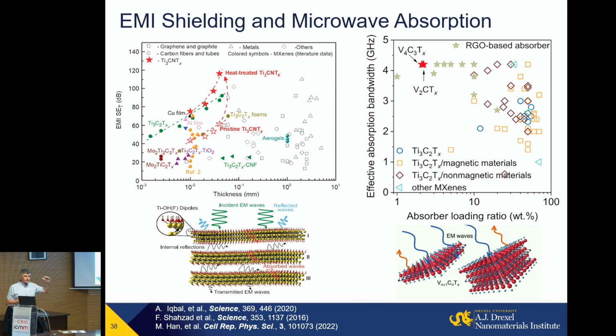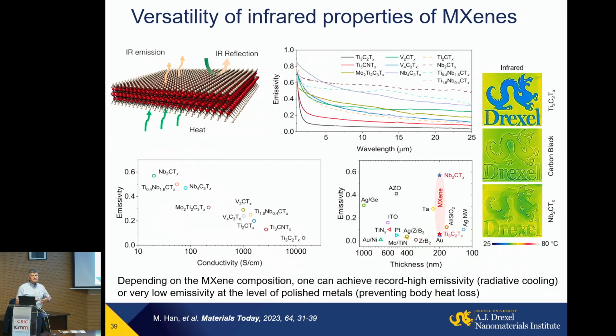And this is what I think is important. We need to look for properties where a material outperforms all known materials and go after those applications. And actually in another paper with the same collaborators, Chong Min Koo, in 2020, we showed that titanium carbonitride MXene in a porous structure outperforms even metals at the same thickness in its ability to shield. And we still don't understand completely the physics behind this. So there is lots of interesting physics to study. I omitted it from my presentation today, but a lot of interesting stuff. But you take another MXene, vanadium carbide. This one, at very small addition, very successfully absorbs electromagnetic waves when dispersed in materials, because it has very different dielectric properties compared to titanium carbide MXenes. The same is true with many, many others.